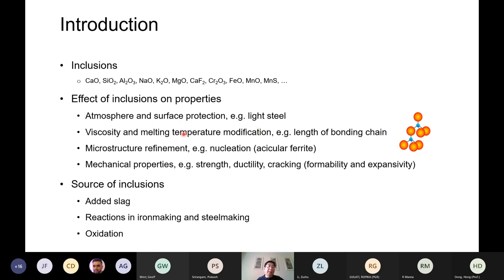And when we have those oxides on the surface, we need to control their properties, including, for example, the viscosity. We need to control the viscosity of the oxide mixture at the surface. And we also want to control the melting temperature, because a lot of oxides have very high melting temperatures. We don't want them to solidify at temperatures below the melting temperature of the liquid steel. So in that case, we need to introduce other oxides to react with some of the oxides to get the right viscosity and the right melting temperature.